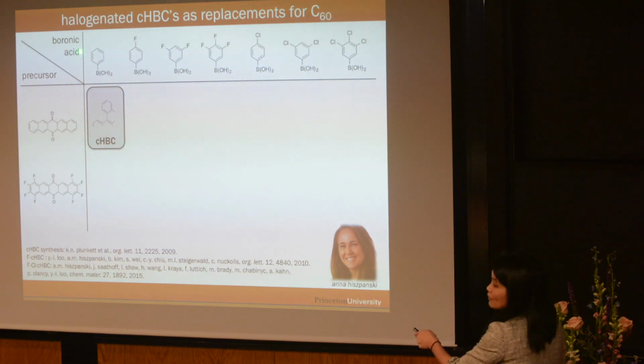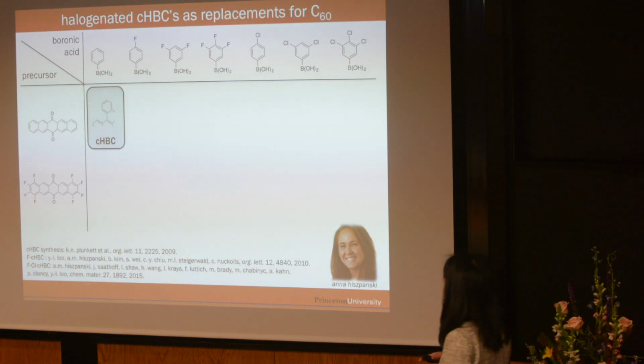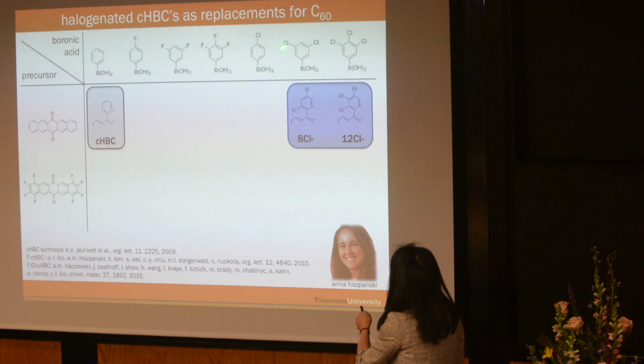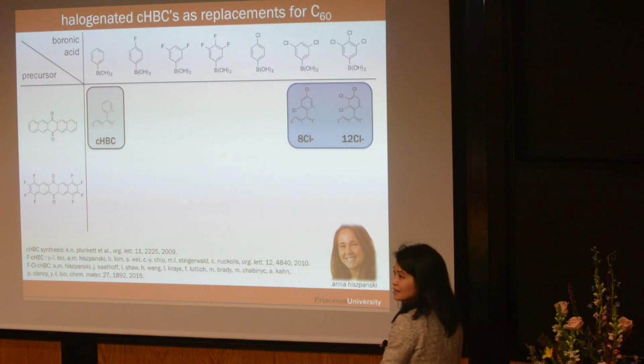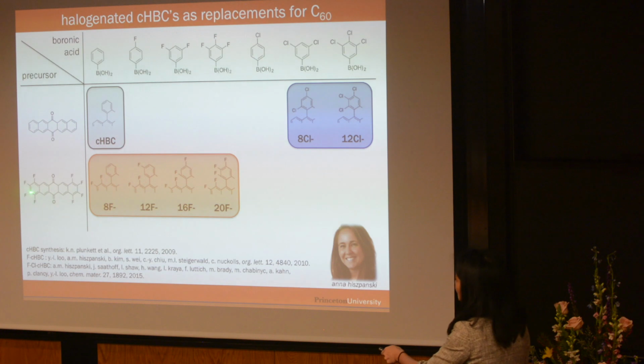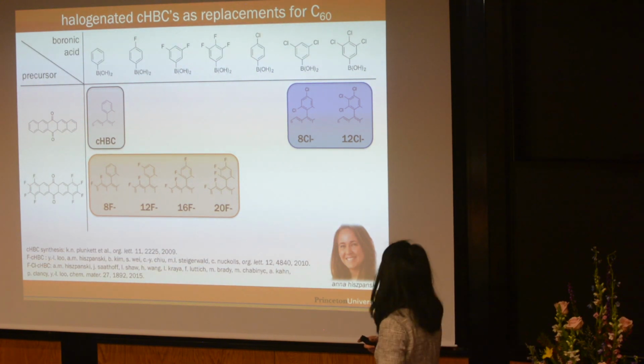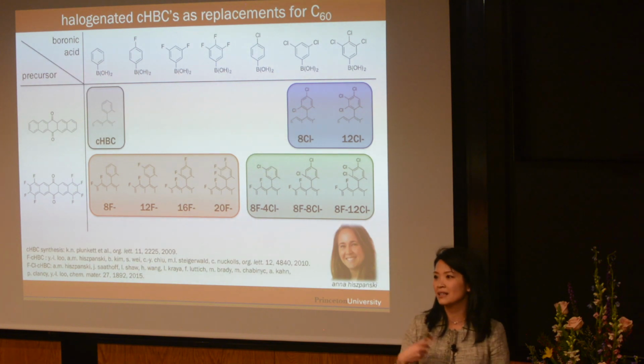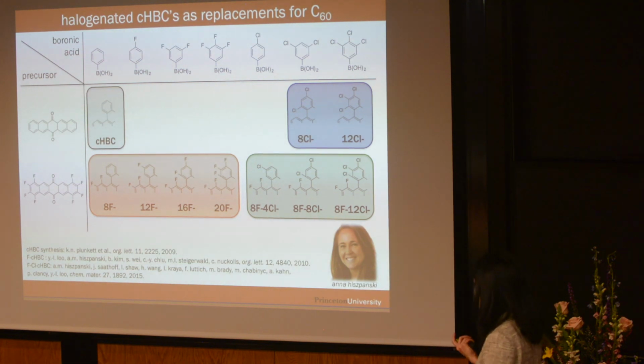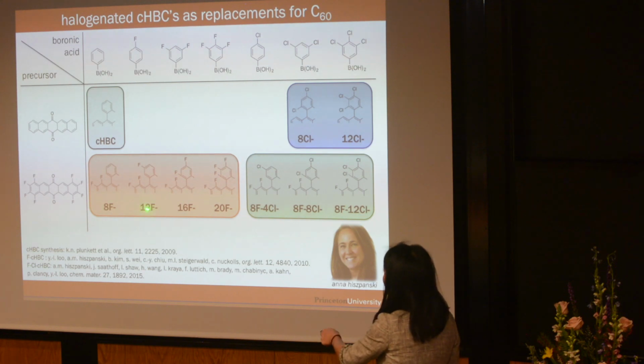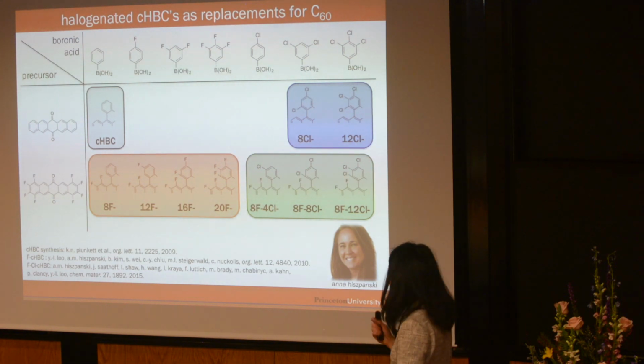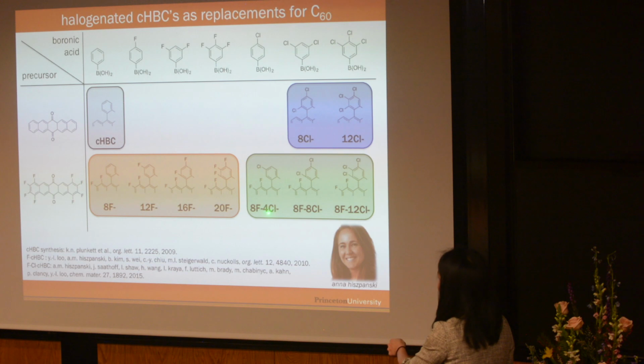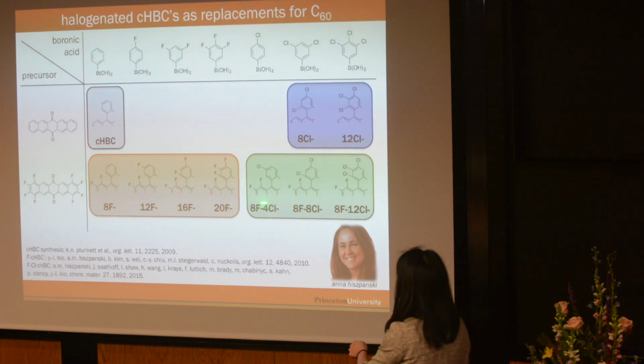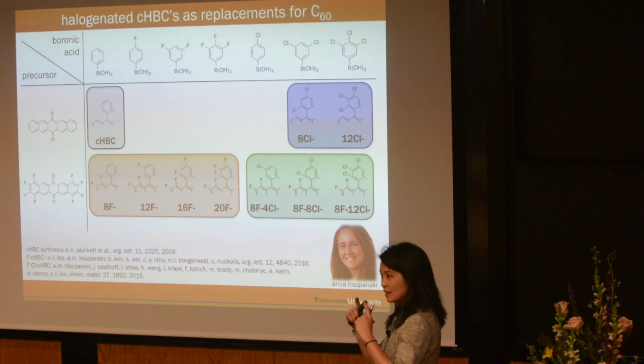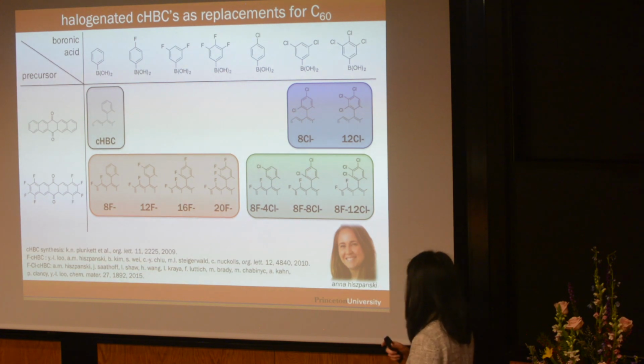And now if you use the phenylboronic acid, you get the parent compound. If you use the chlorinated boronic acid, you can access the chlorinated compounds. If you start with the fluorinated and then you use the fluorinated boronic acid, you can access the fluorinated compound, and then you can access a fluorinated chlorinated compound. We're not very creative with our naming schemes. The numbers in front just represent how many halogens there are. So this is 8 fluorines and 4 chlorines. I'm only showing you a quadrant because the chemical structure is actually symmetric.